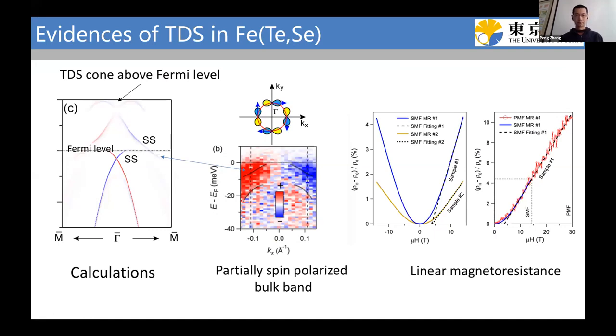We also go back to the topological Dirac metal state in iron tellurium selenium. Since the bulk Dirac cone is above the Fermi level, we cannot directly resolve it from ARPES, but we found some indirect evidence. First, we found that the dyz band, which should be a bulk band, shows some partial spin polarization. We found that this spin polarization should be induced by this cone structure. Also, we measured the magnetoresistance of this material, and we found a very good linear magnetoresistance up to 30 Tesla, which also suggests the existence of a bulk Dirac cone in this material.